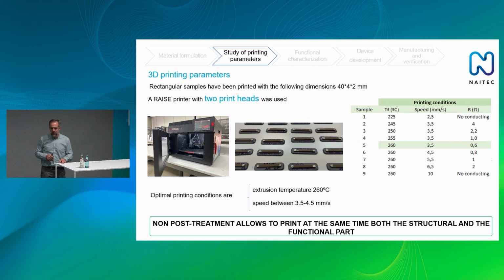After having the optimized formulation, we also study the parameters for printing, different temperature and speeds to guarantee the best conductivity of the final samples. And these are the conditions that we found to be optimum: 260 degrees and between 3.5 and 4.5 millimeters per second. And the resistivity that you see here is without post-treatment.